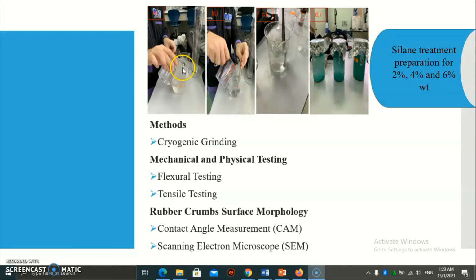This figure shows the silane treatment preparation for 2%, 4%, and 6% weight percentage. The first step is water to alcohol agitation. The silane is mixed with water and alcohol and stirred together, and the rubber crumb is poured into the solution. After that, it is soaked for 3 hours.